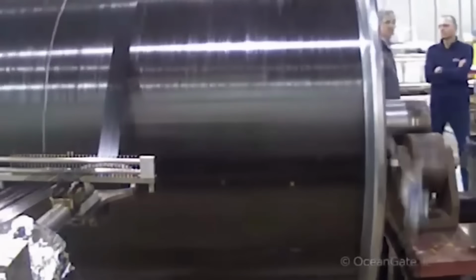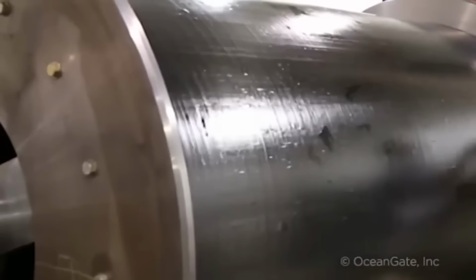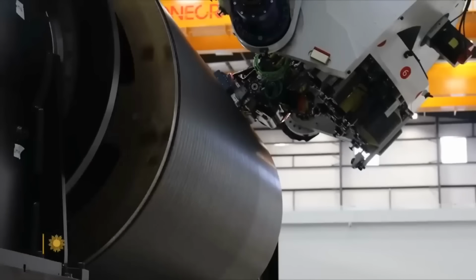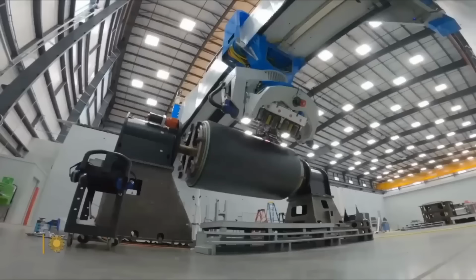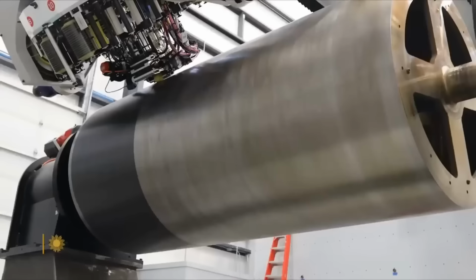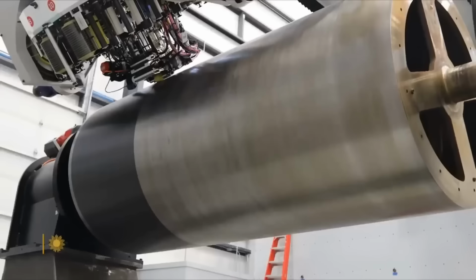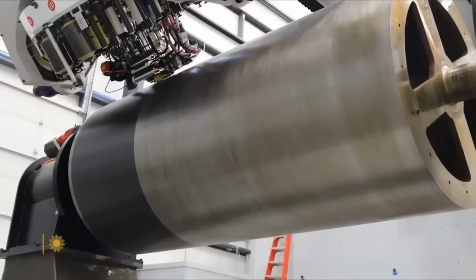Carbon fibers, typically pre-impregnated with resin, known as prepreg, or dry fibers that are wetted with resin during the winding process, are fed from spools through tensioners to the winding head. The mandrel rotates while the winding head moves along its length, laying down the fibers in specific patterns. Multiple layers of carbon fiber are applied to build up the desired wall thickness.